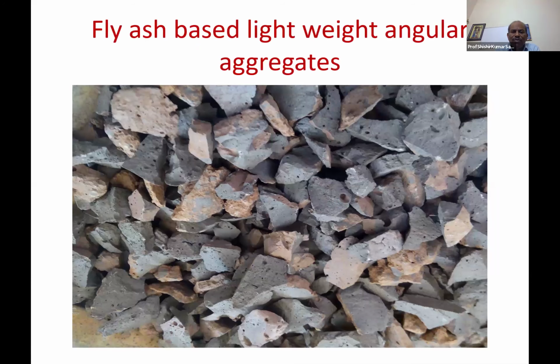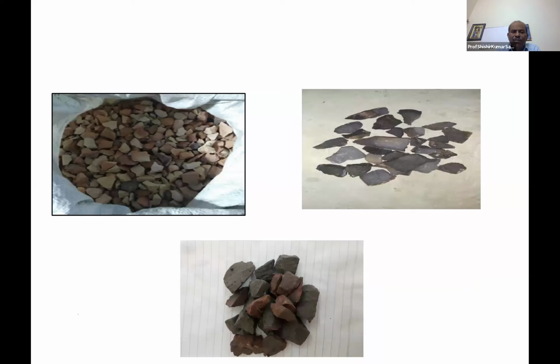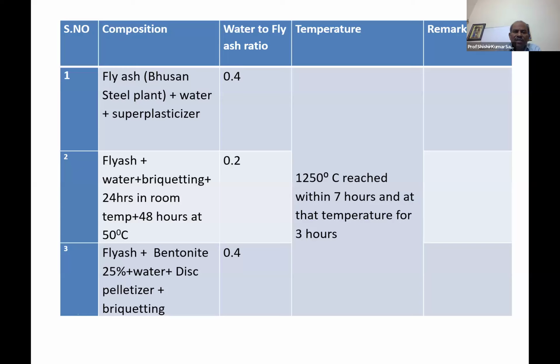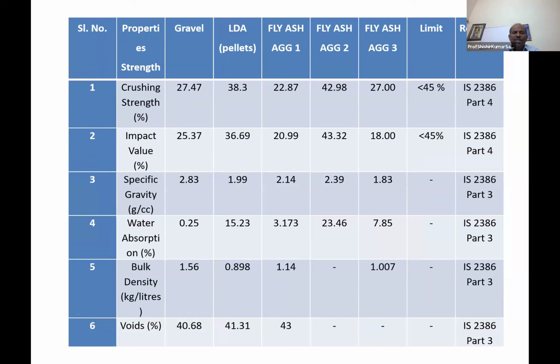Fly ash based lightweight angular aggregates. These are multiple trials we have done, and finally this aggregate, the bottom one, also with admixture we have got. Yes, this one, 1250, 7 hours, briquetting. And this aggregate shows this property, crushing strength. So 2-3 types we have done through 2-3 processes: aggregate 1, aggregate 2, aggregate 3.